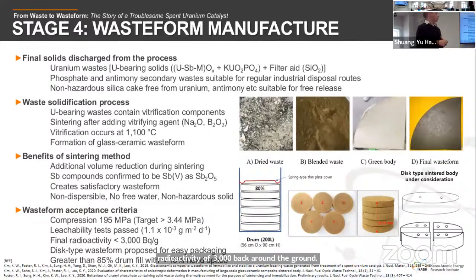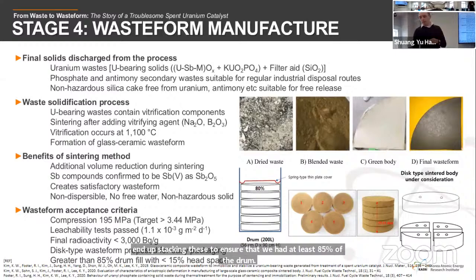In terms of final waste, here we've got the dried waste, blended waste, the green body, and the final sintered body. These were for going into 200-liter drums. The final disposal, we settled on a disc type system, so we could end up stacking these to ensure that we had at least 85% of the drum filled, so we didn't have to worry about that to also meet that requirement.